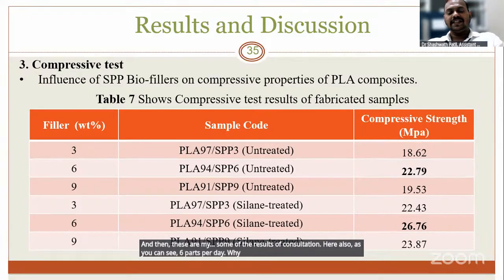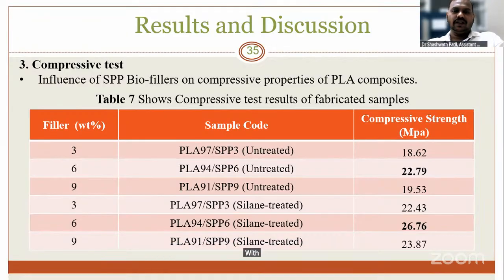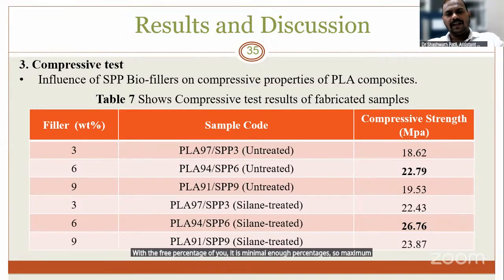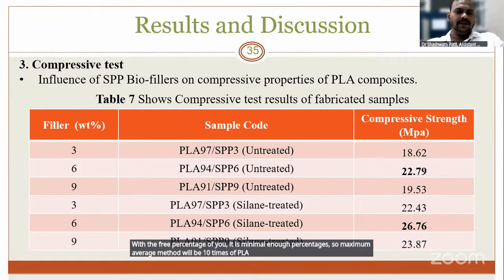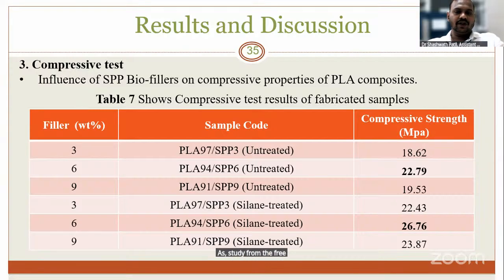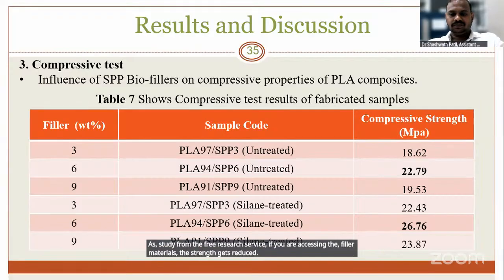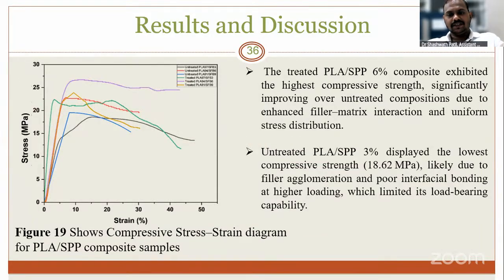Why is this 6% giving more strength? With 3%, it is a minimal filler percentage, so the maximum matrix material will be PLA only, so it shows limited strength. As for the excessive 9% filler, it also reduces strength compared to the 6%. As per the literature studies, if you add excessive filler material, the strength gets reduced. So this treated 6% composite exhibited the highest compressive strength, significantly over the untreated sample.